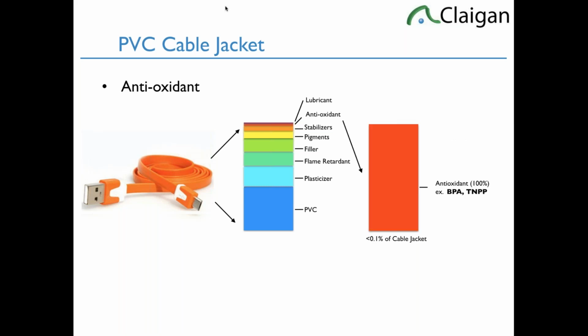And then there's the antioxidant. Usually the PVC itself has an antioxidant. However, rarely is the BPA antioxidant in PVC above 0.1%. It's normally from the plasticizer. It's the high concentration antioxidant in the plasticizer. The antioxidant, again, making it so when the PVC is extruded or otherwise processed, it doesn't react with oxygen and create a burnt effect, which is like color or oxidation, a color change, and possibly a materials change. It's often antioxidant, but almost always, if it's part of the base resin, it's well under 0.1%. When it's above 0.1% by weight, like bisphenol A can be in PVC, it's normally coming in through the plasticizer.